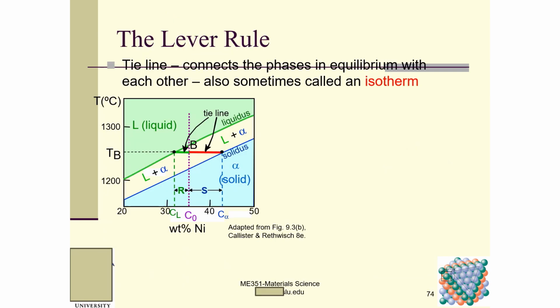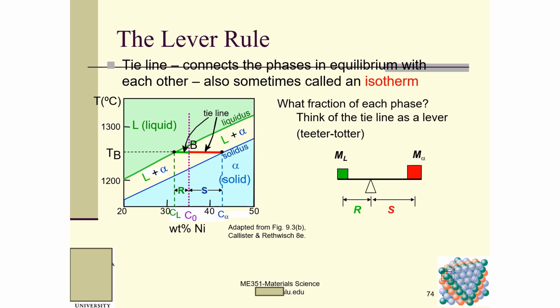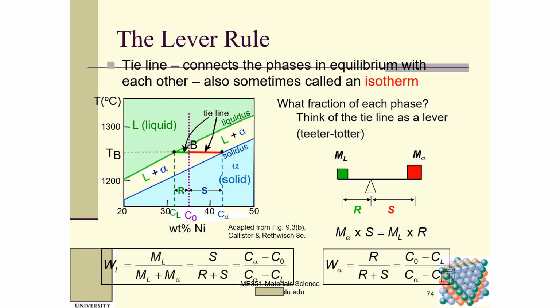So these are the three rules. This is called the lever rule. The tie line connects the phases in equilibrium with each other, and is also sometimes called an isotherm. Therm means temperature, right? So what is the fraction of each phase? Think of the tie line as a lever, with the fulcrum at the total composition. This is R and S. So the balance is M alpha multiplied by S equals ML multiplied by R. So we can get WL equals ML over ML plus M alpha, equals this. And similarly, we can get alpha.